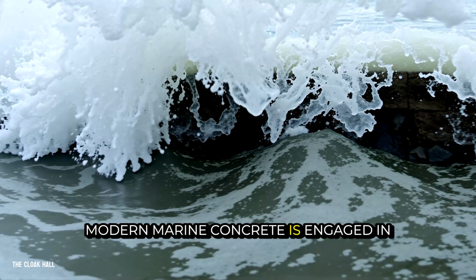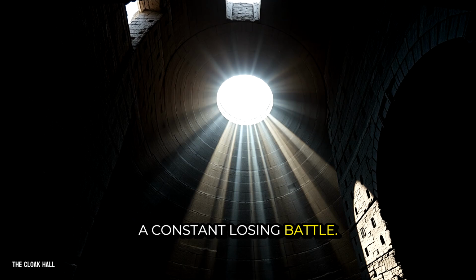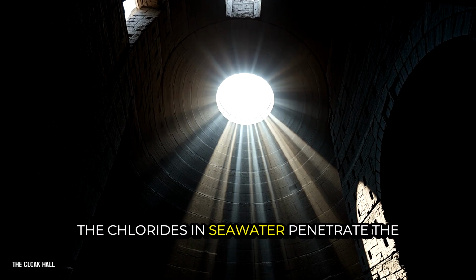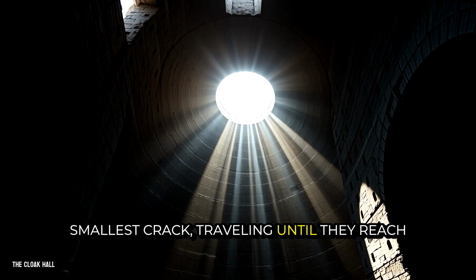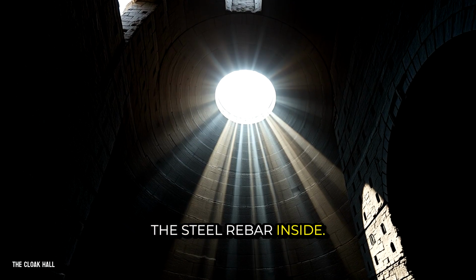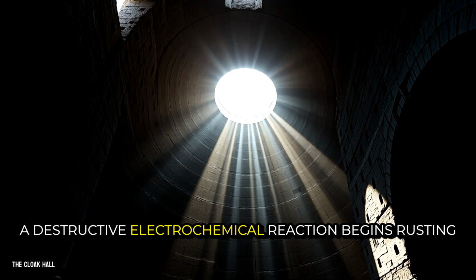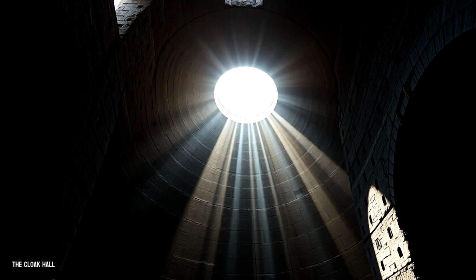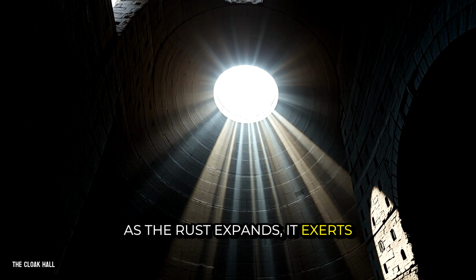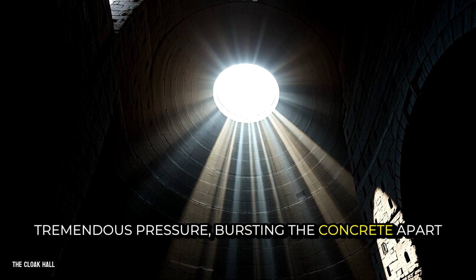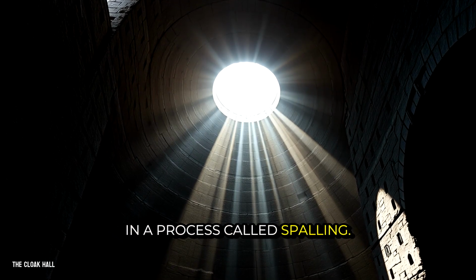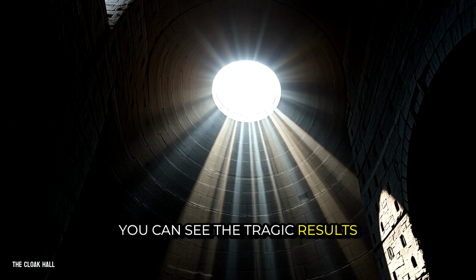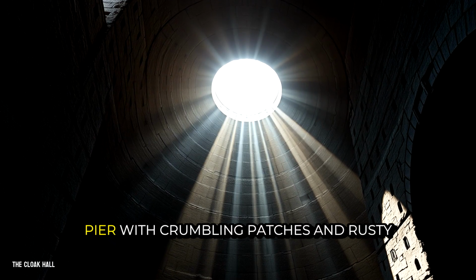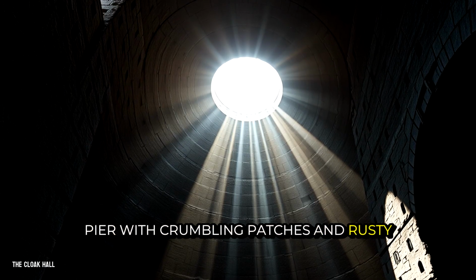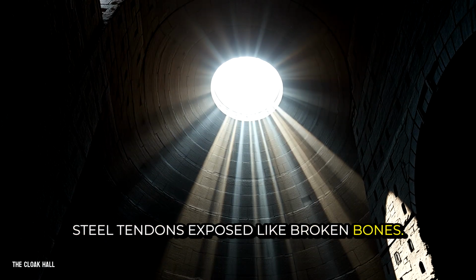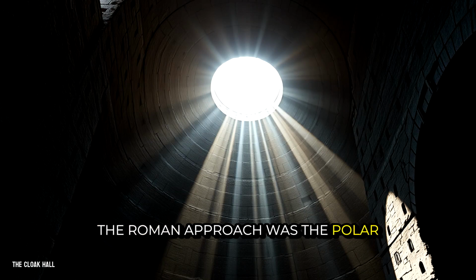Modern marine concrete is engaged in a constant, losing battle. The chlorides in seawater penetrate the smallest crack, traveling until they reach the steel rebar inside. A destructive electrochemical reaction begins, rusting the metal. As the rust expands, it exerts tremendous pressure, bursting the concrete apart in a process called spalling. You can see the tragic results on any aging coastal bridge or pier, with crumbling patches and rusty steel tendons exposed like broken bones. The Roman approach was the polar opposite.